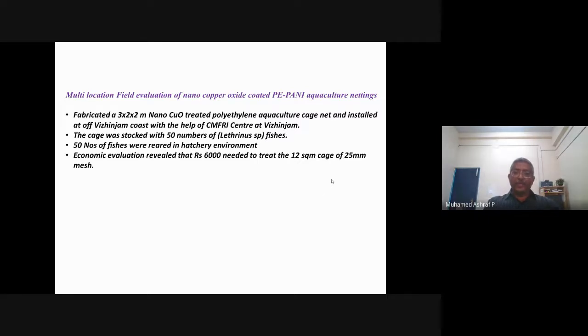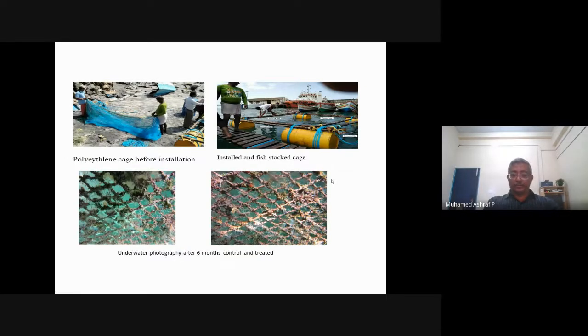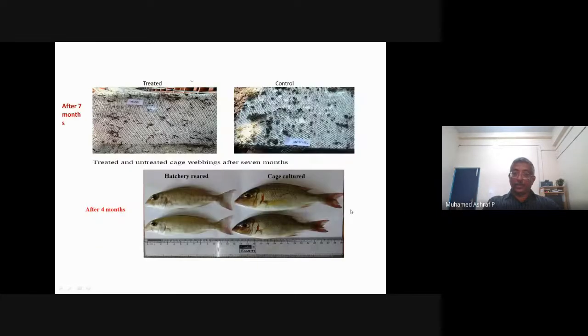And what we have found, the economic evaluation found that 6,000 rupees are needed to treat the 12 square meter of a cage. And these are all the arrangements while we are installing the net. Then you can see the underwater images of the control and the treated one. And these are all the situations after taking out. The control was here and this is the treated one.